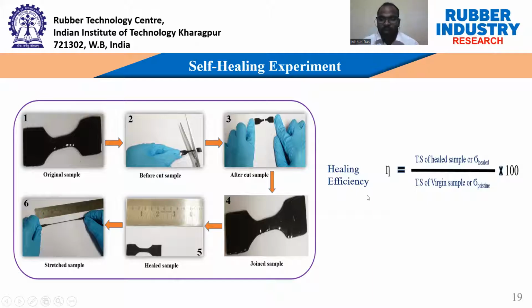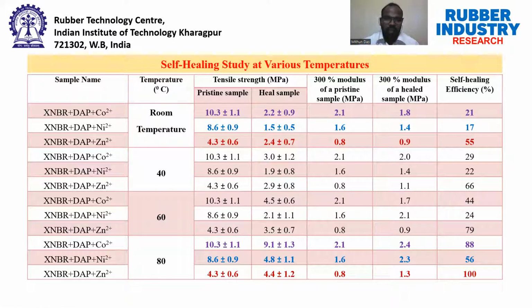We calculated the self-healing efficiency based on the tensile strength of the healed sample divided by the tensile strength of the pristine sample multiplied by 100. And then we calculated the self-healing efficiency of the various metal ligand modified rubber compounds at various temperatures, starting from room temperature up to 80 degrees centigrade. At room temperature, the cobalt modified compound has a healing efficiency of 21%, the nickel modified compound 17%, and the zinc modified compound 55%. So that means zinc can form more weak and dynamic coordination bonds compared to cobalt and nickel. As the temperature increases, the self-healing efficiency also increases gradually.